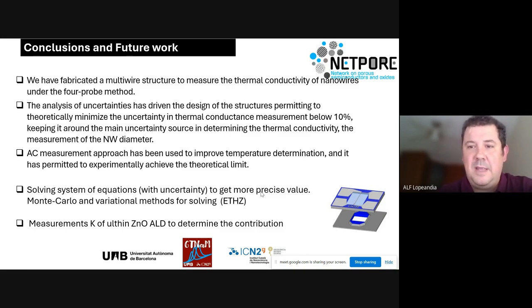And I wanted to say that the reduction of the uncertainty has been potentiated by the use of the AC measurements, which has improved the temperature determination and has permitted us to experimentally achieve the theoretical Johnson-Nyquist limit in most of the measurements. Nowadays, and this is future work, we are solving the system equations with uncertainty to get more precise values, even though I'm quite confident of the values that we are showing.